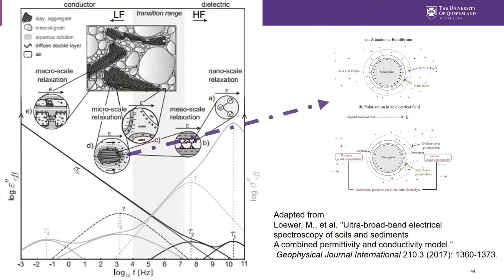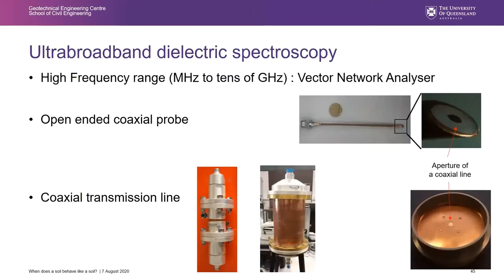And then finally, if we go to the very, very low frequency range, we have this membrane polarization. It means that when you apply an electric field at very, very low frequency, the ions are going to stick to the big pore throats and create this typical relaxation. So as you can see, it's not that easy because you have very different processes depending on the scale and the frequency range. To be able to fully understand these processes, we need to measure accurately the electromagnetic properties of soil over this whole frequency range. This is what we've been doing a lot here at UQ. Can you move to the next slide, Alex, please?